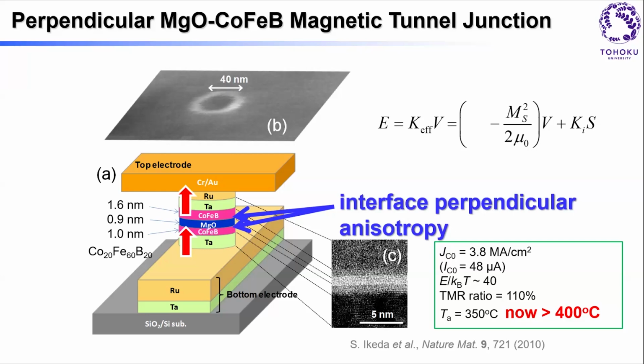And this is volume times surface, or volume is surface times thickness. So in order for this second term to win over the first term, we have to make the layer thin. And these are 1.6, 1.0, extremely thin compared to those thicknesses that people used to use in experiments these days.